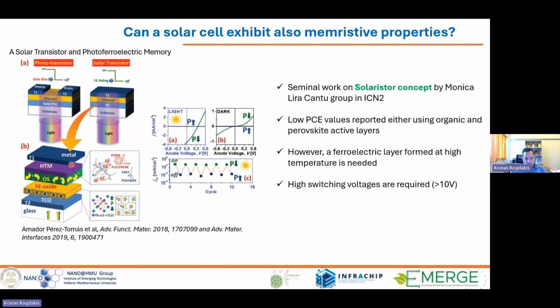Ferroelectric means it's a material that can be polarized by applying an electric field, and they showed that they can tune the resistance of the device by polarizing or not this layer, and also, of course, they can tune the resistance by turning on light illumination because it's a solar cell. However, in their device concept, this ferroelectric layer required a very high temperature to develop it, more than 500 degrees. And also, they need to apply more than 10 volts to switch the polarization of the film, more than 10 volts. So both of these make the device incompatible with low temperature manufacturing, it cannot be, let's say, printed, cannot be on flexible devices, and also requires high power for its operation.